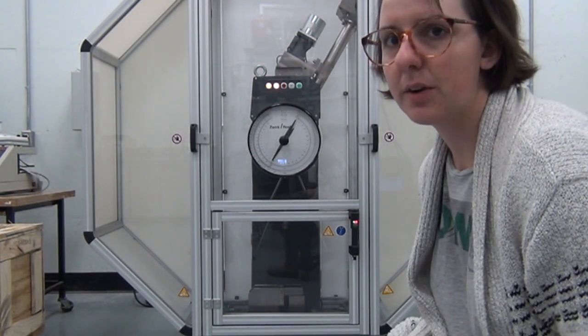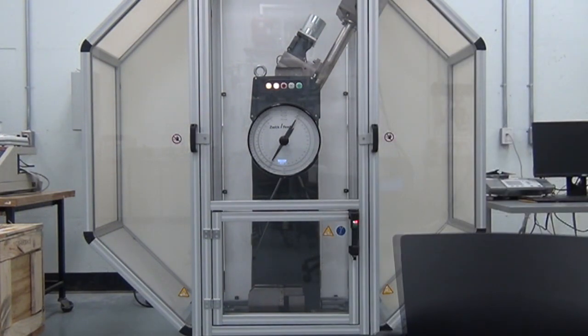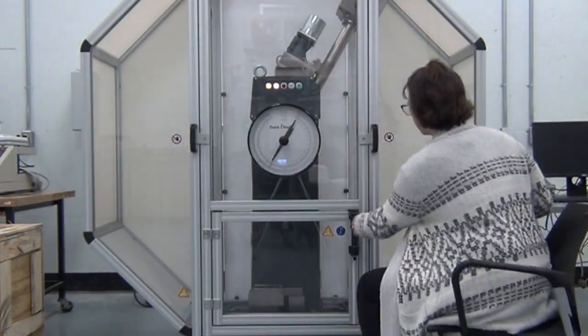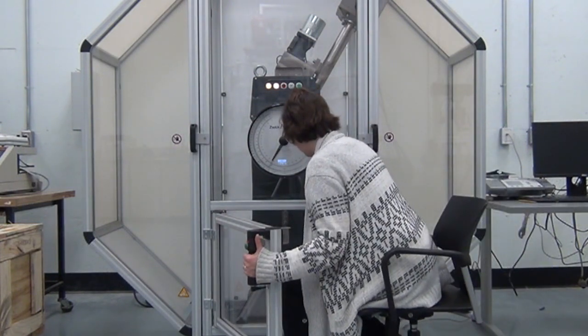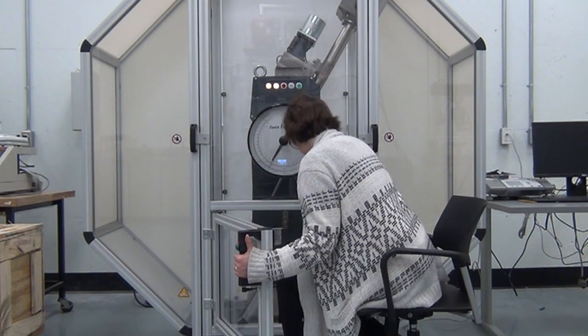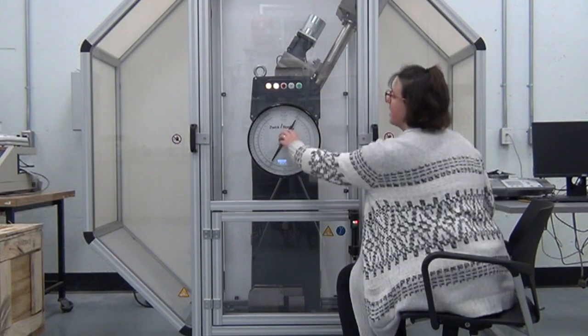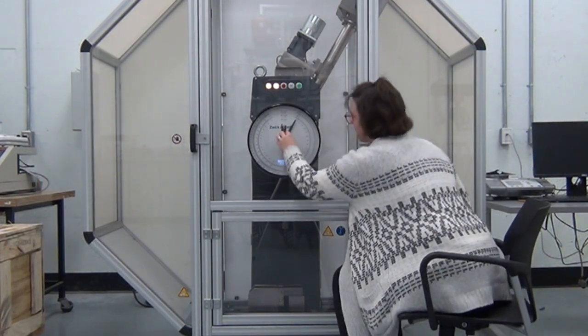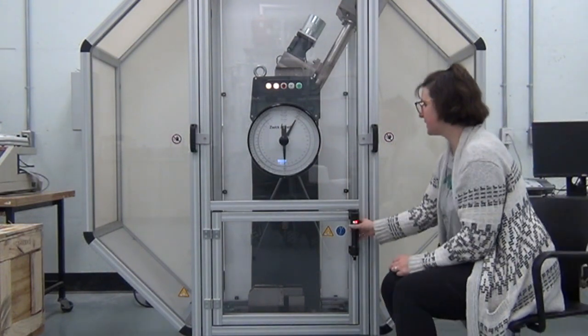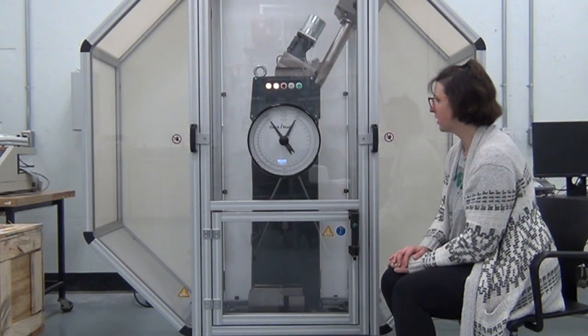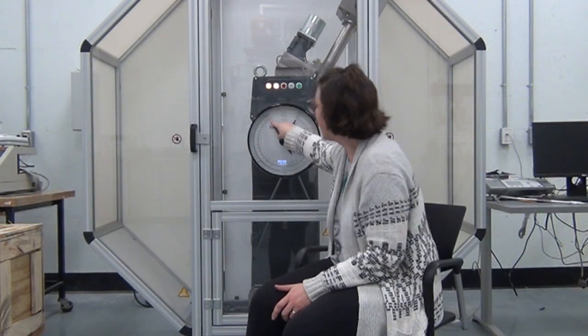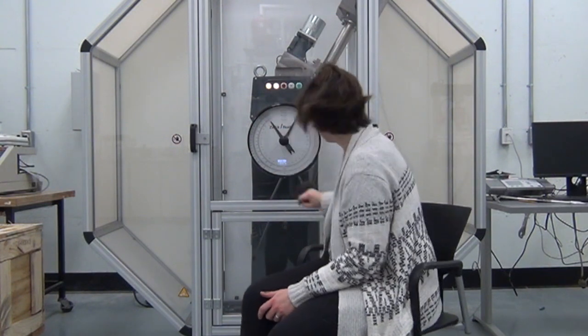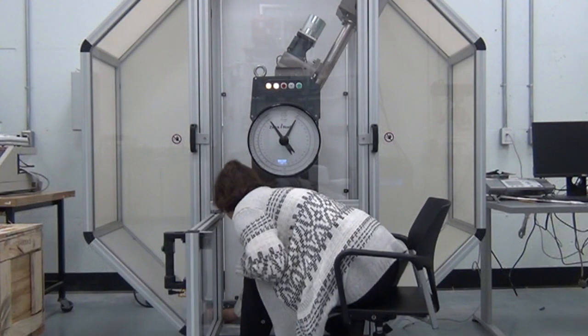I'm going to grab the dry ice sample. So I've got my dry ice sample in the tongs. I'm going to place it in the machine just like before. With the notch facing out, I'm going to zero the machine again. And I can run my test. So these results are quite different than our room temperature sample. We can see already that the dial swung all the way back to around 3 joules. If I go retrieve my sample, oh, that's cold.